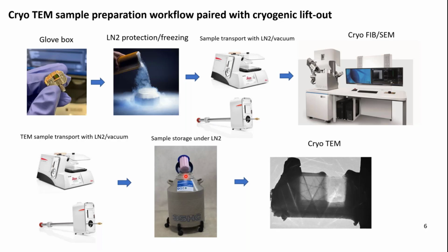Then what accelerating voltage did you use for the TEM analysis? Oh, I have only used 200 kV. The reason why is I believe radiolysis can be significantly lowered at high accelerating voltage. And if I change to 80 kV, it's really a hassle because I have used the dedicated probe-corrected STEM, so if I change from one to another, it will bother other users. So I have used 200 kV. Another reason why I stick to using the same voltage is the radiolysis. And I use JEOL NEOARM for doing that.